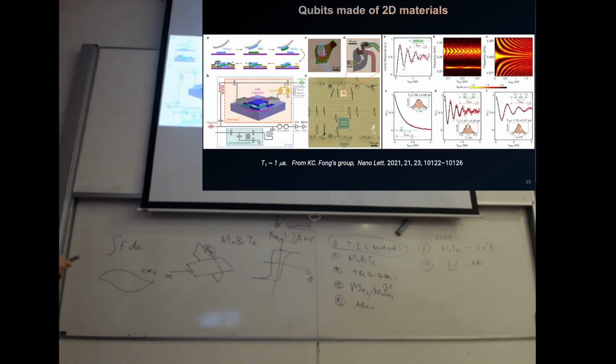And K.C. Fong's group showed another example. What they did is not use the material directly as a Josephson junction. Instead of doing a Josephson junction, they make a large capacitor for this transmon technology. And this niobium diselenide, two layers with the hBN in the middle, plays the role of the capacitor. And this gives rise to the functioning of a two-dimensional capacitor-assisted transmon platform, which shows a lifetime of about 1 microsecond.